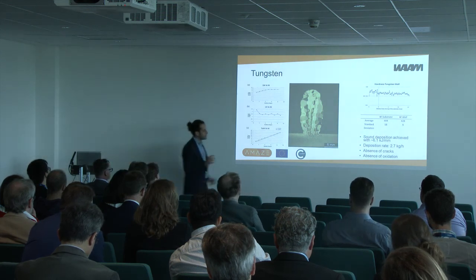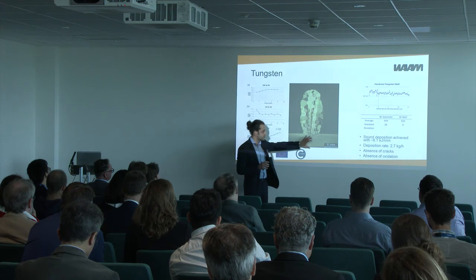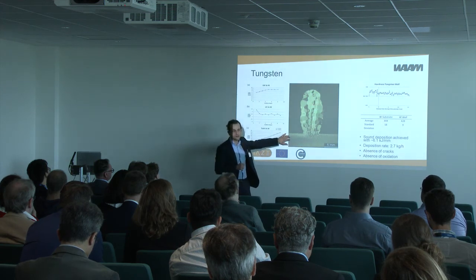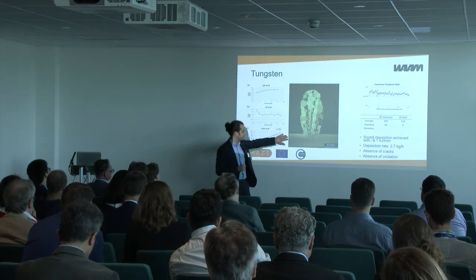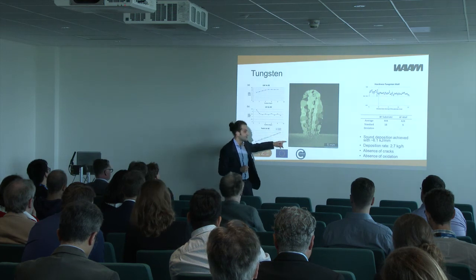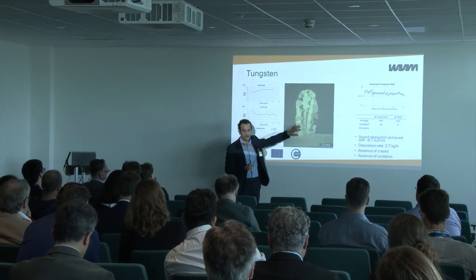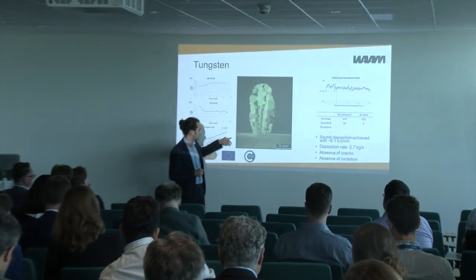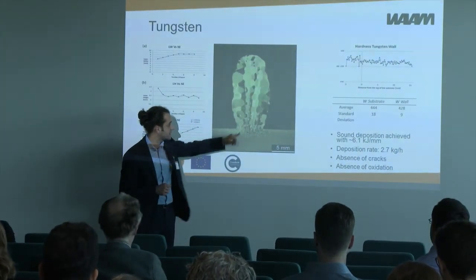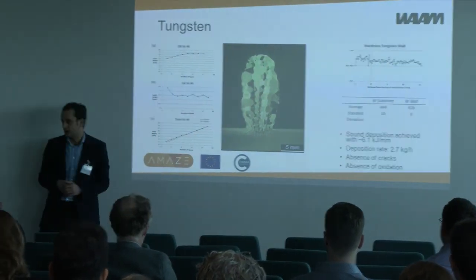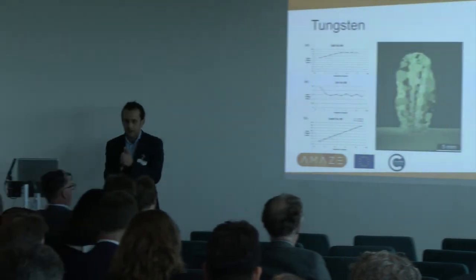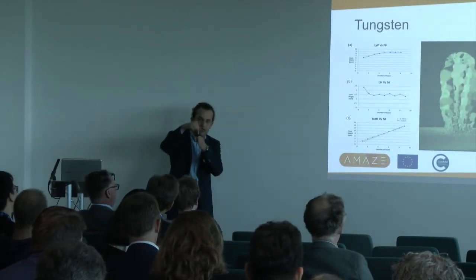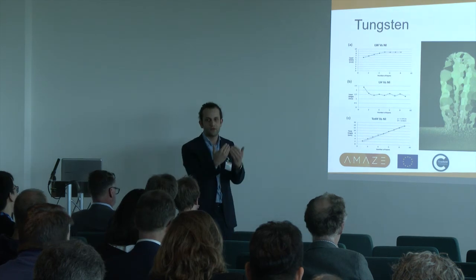And critically, you can see here it was made on a plate which was flat. We abandoned this option immediately because we had cracks coming from the edges of the substrate. So the material was not cracking at all. Our material was good. The cracks were coming from here and then eventually traveling inside and then breaking samples. So what we did was flipping the plate by 90 degrees and depositing on the edge. So there were no open edges for the crack to start.